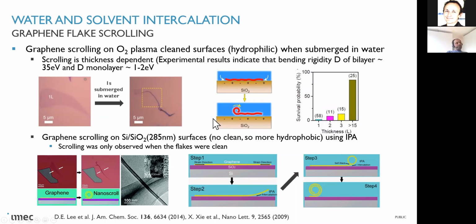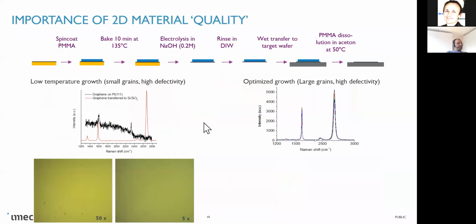And it's the way around, it's also working if you have a hydrophobic surface and you put the graphene on top and you put it in a solvent, well, you can have exactly the same mechanism. And this is something that we saw a lot, especially for high quality material, is that as soon as we are bringing in any kind of solvent, we have a scrolling up mechanism that is happening here.